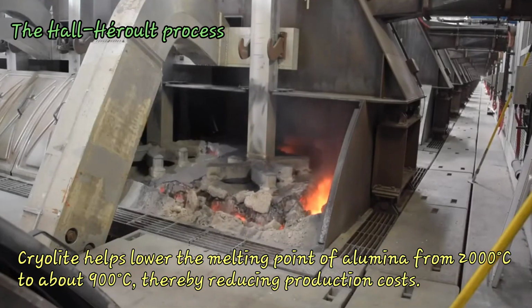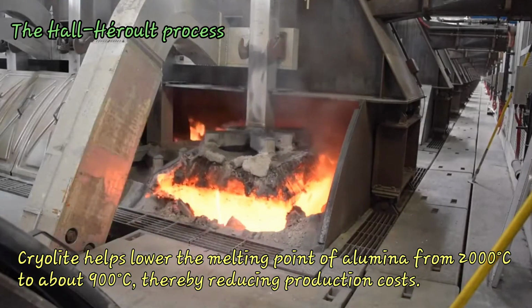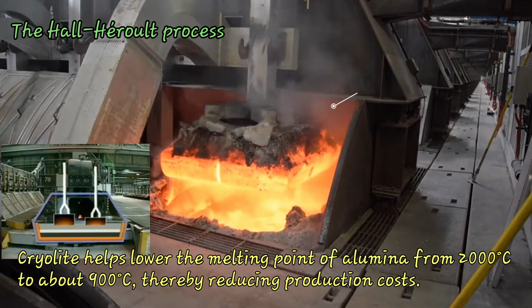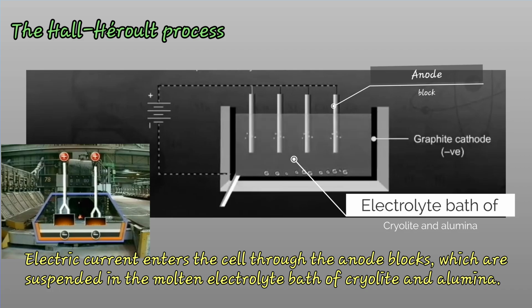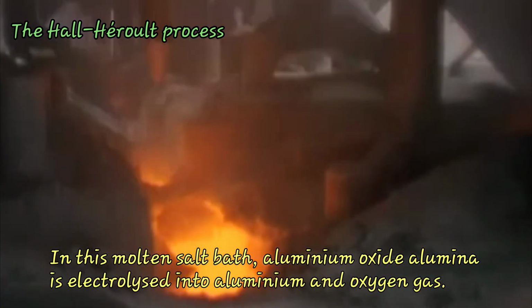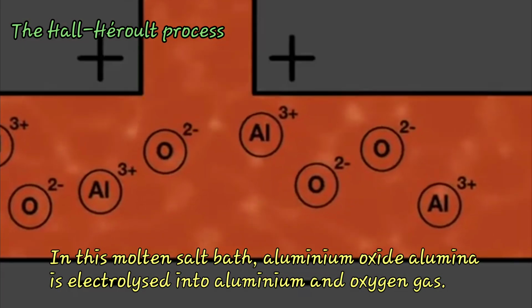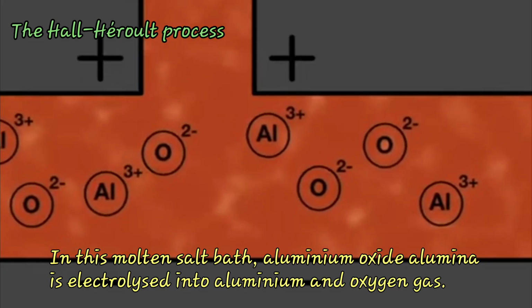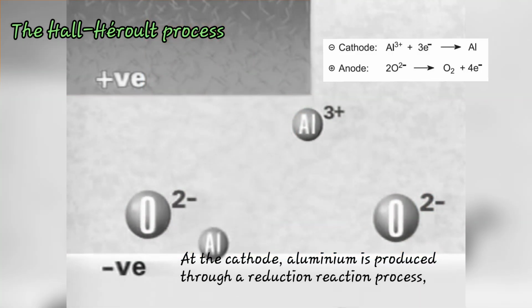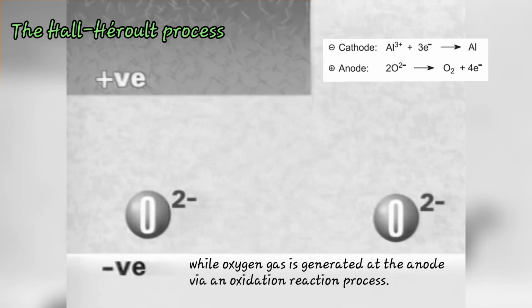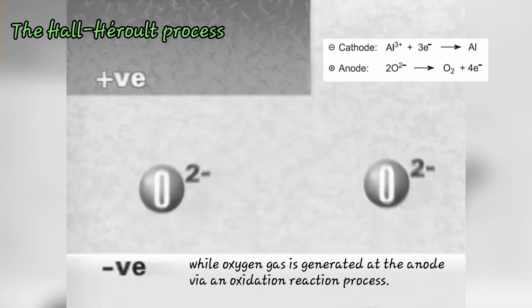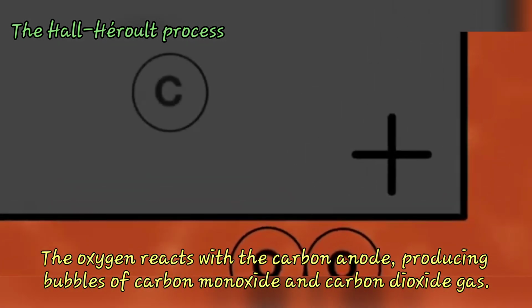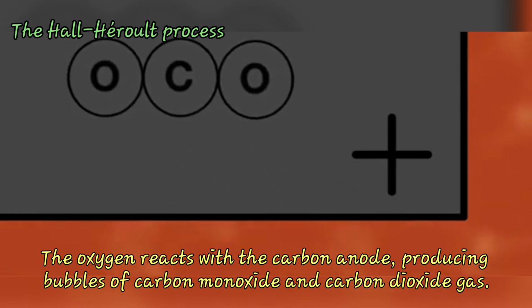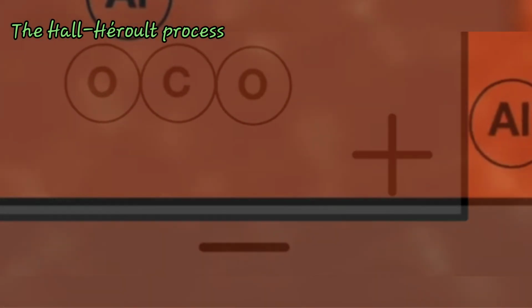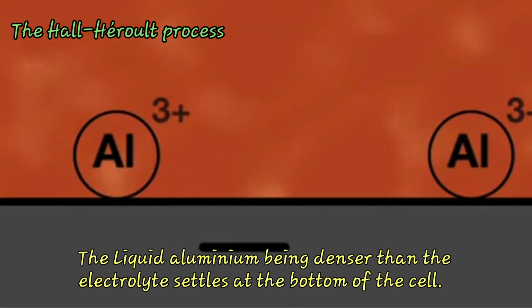Cryolite helps lower the melting point of alumina from 2000 degrees Celsius to about 900 degrees Celsius, thereby reducing production costs. Electric current enters the cell through the anode blocks, which are suspended in the molten electrolyte bath of cryolite and alumina. In this molten salt bath, aluminium oxide, alumina, is electrolyzed into aluminium and oxygen gas. At the cathode, aluminium is produced through a reduction reaction process, while oxygen gas is generated at the anode via an oxidation reaction process. The oxygen reacts with the carbon anode, producing bubbles of carbon monoxide and carbon dioxide gas. The liquid aluminium, being denser than the electrolyte, settles at the bottom of the cell.